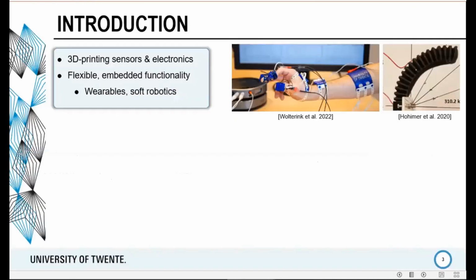So our group mainly focuses on 3D printing with fused deposition modeling, and then we focus on printing sensors and electronics. Fused deposition modeling is the desktop method for 3D printing. So you have an extruder which extrudes a molten plastic line by line, layer by layer, to create your geometry. And this is interesting for printing sensors and electronics because it's low cost, it's very simple, and it allows for multi-material prints. So we can print up to 5 materials in one print with the same machine. That's very interesting because most printing techniques are limited to one material because you cannot switch during the process.